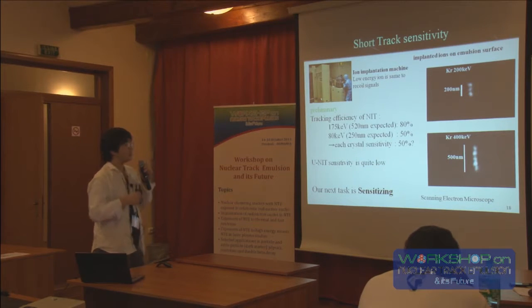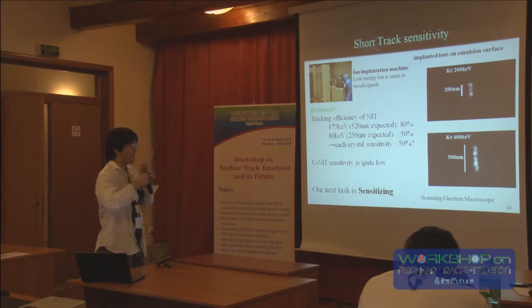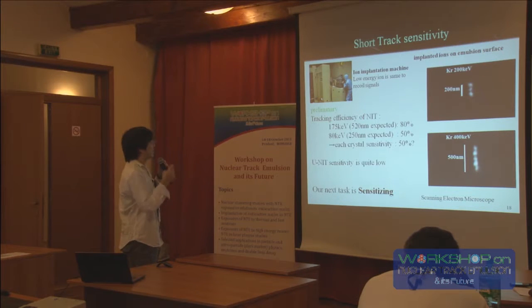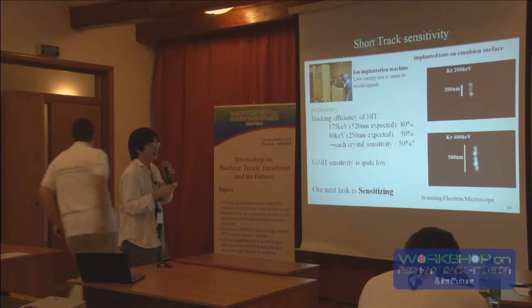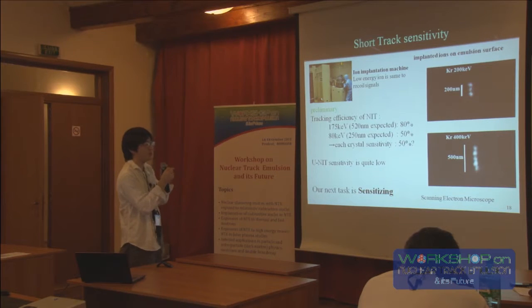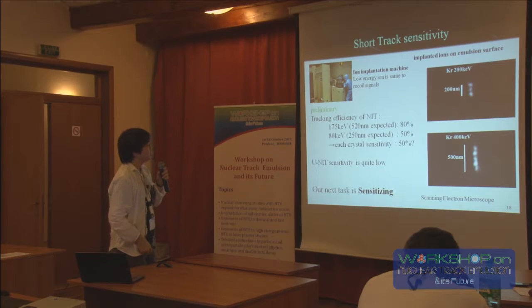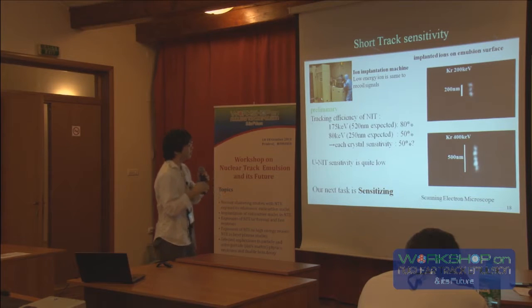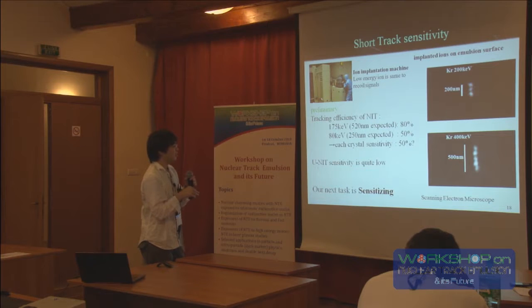It depends on the zooming rate, but the main problem is that the electron microscope needs to cut the samples, and only very small samples can be used. The scanning electron microscope is very low speed, and the transmission electron microscope is relatively high speed, so maybe speed is not a problem there, but it is very destructive observation, so it cannot be used for other experiments.